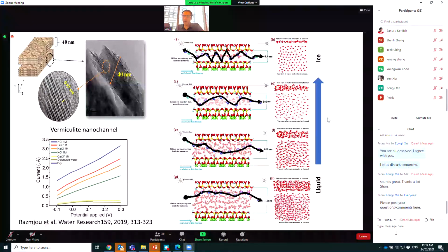The other thing that we found when we reduced the nanochannel size, which other people have also addressed, is that the behavior of water molecules changes when you confine water molecules into a sub-nanometer channel. So water molecules form ice formation at room temperature, and that changed the concept, changed lots of things, because you don't have water inside the nanochannel. You have a molecule that exhibits like ice, and dealing with a very rigid structure is a bit difficult.